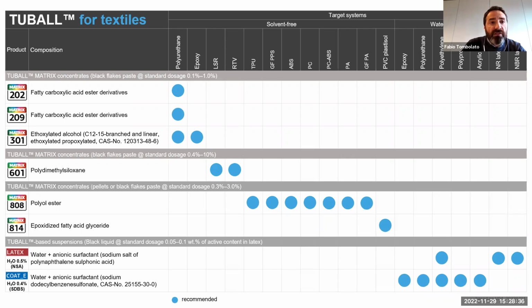MATRIX concentrates differ from one another by the quantity of graphene nanotubes that are inside, but also by the carrier that is used to prepare the concentrate, which is specifically designed according to the target chemistry system. We have dispersing systems like plasticizer, like reactive diluent, or even polymers. For water-based suspensions, graphene nanotubes are stabilized in water using anionic surfactants.